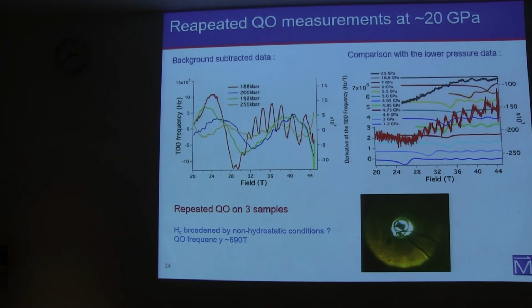The first comment I would like to make is that 20 GPa is way beyond the hydrostatic limit of any known pressure medium. I was using methanol ethanol, and methanol ethanol is no longer hydrostatic from 10 GPa and above. This is a technical point, but usually quantum oscillations are destroyed by non-hydrostatic conditions. So the fact that we did observe quantum oscillations was just exceptional in itself at such a high pressure. And again, 20 GPa is really difficult to get with leads that have to go through a gasket, and there's a very high failure rate for that type of pressure range.